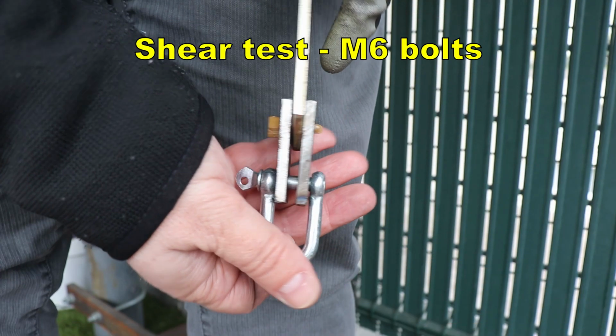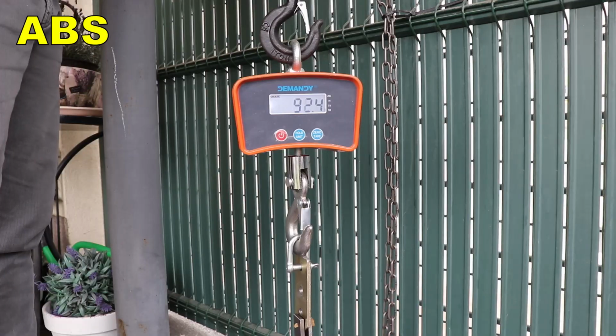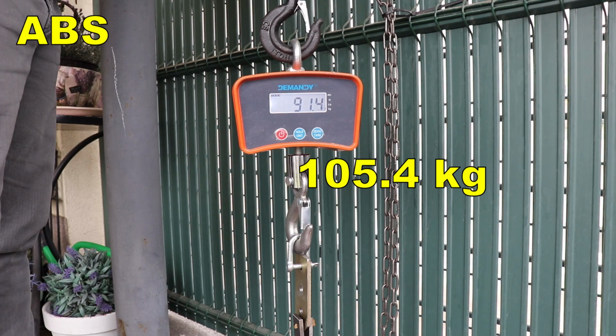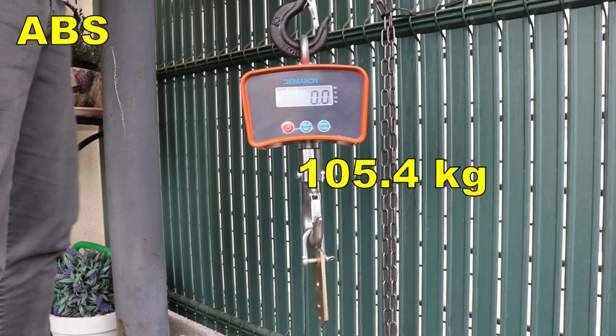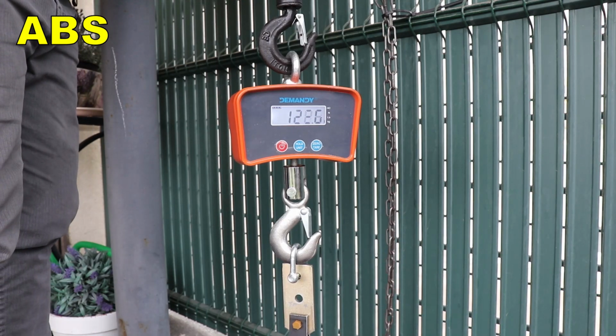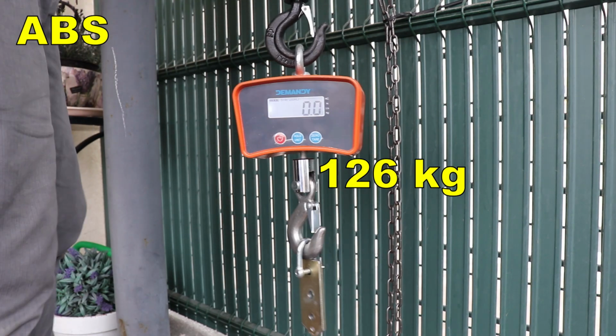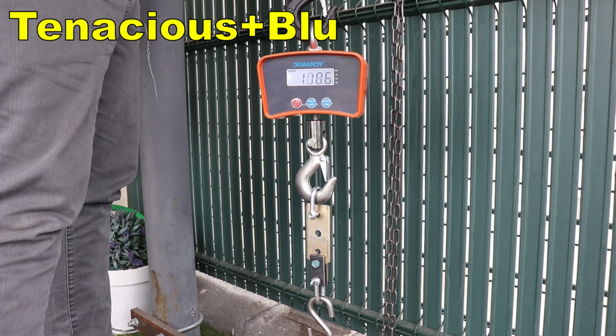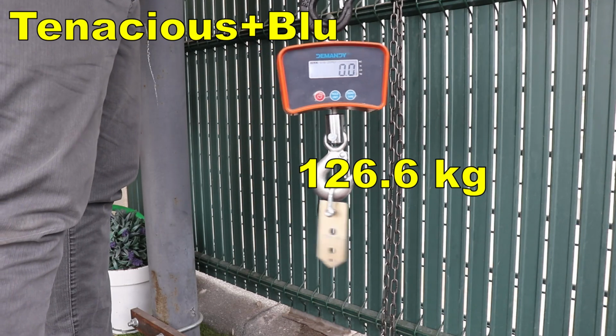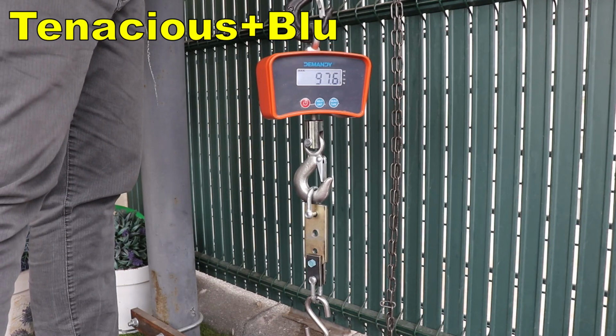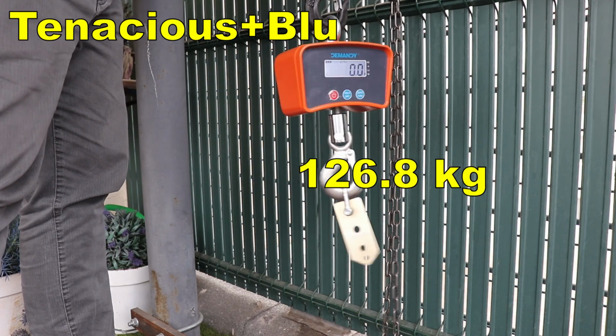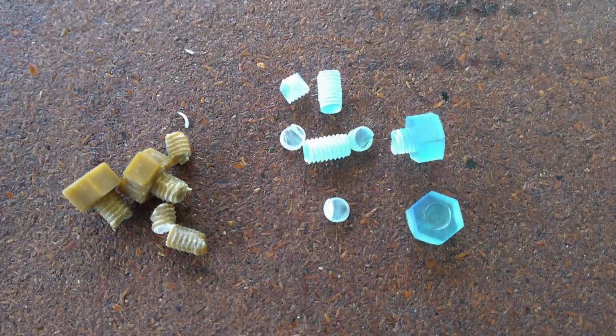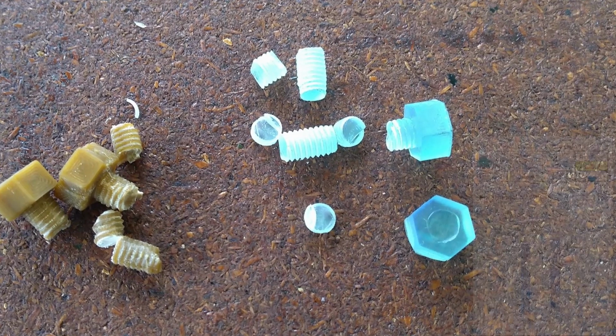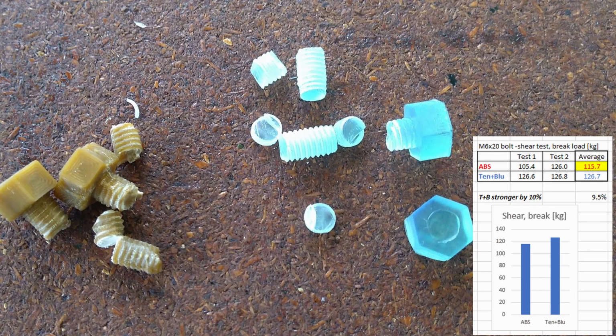And this is my setup for shear stress. This is two-sided shear stress, so it is a pure shear without any bending or similar. And I'm recording here the maximum load, because sometimes it reached the maximum load at the start of the shearing, and then I can measure lower values. And here you can see they sheared approximately at the correct two positions. And here the resin was stronger by approximately 10%.